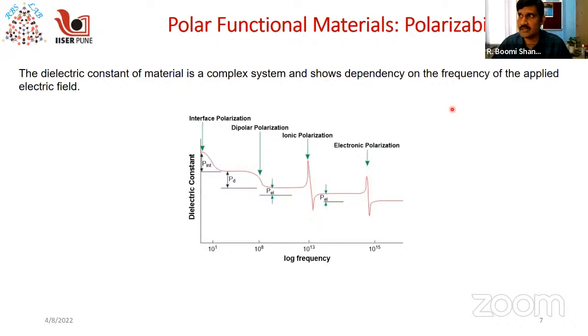If you change the applied electric field frequency, the polarization mechanisms will vary. For example, if you perform the experiment at very low frequencies, all the 4 polarization mechanisms will be prevalent. But as you increase the frequency, one of the polarizations will be reduced. For example, the interfacial polarization, the space charge polarization, will go off. This is around 10 power 3 to 4 in frequency. Since I have plotted it in the log scale, you will see positive log frequencies.